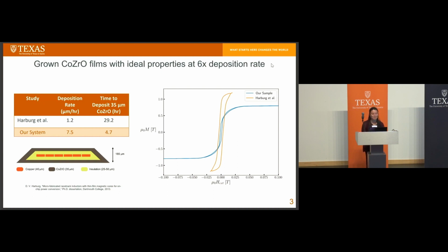So first, our sputtering system today can sputter cobalt zirconium oxide films at rates that are much higher than those in literature. And here I wanted to compare to a specific study. This is a study done by Harburg et al. at Dartmouth, and they were trying to fabricate on-chip inductors as well with cobalt zirconium oxide. Using their system, it took them 29 hours to deposit one of the layers that you can see in the inductor here. With our system, it would take just under 5 hours.